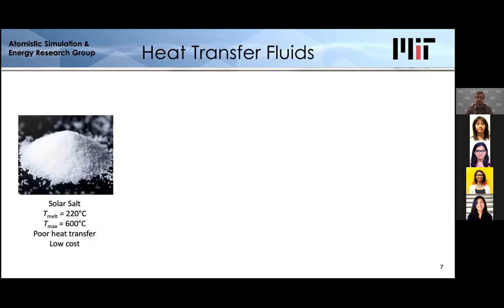So solar salt, it's a nitrate salt combination. It melts at around 220 C. The maximum temperature is around 600 C, so we're pretty much constrained to that temperature range. It has very bad heat transfer performance as well, which I'll get to in a sec why that's important. But it is very low cost. So the idea of this project is, what are some alternative fluids we could propose for this that might improve performance and reduce cost of the overall system?